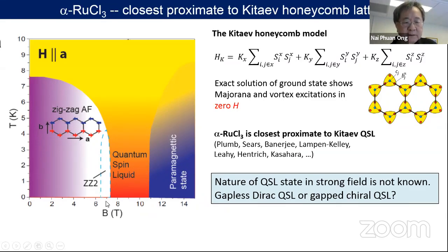At low fields below 7.5 Tesla, you have an ordered state rather than a spin liquid state. And the ordered state is comprised of a zigzag pattern parallel to what's called the zigzag direction, right? Just like in graphene, zigzag means it's going zigzagging here, parallel to the field. And this is called the A-axis in ruthenium chloride. The perpendicular direction, still in the plane, is called the armchair, right? Why? Because this looks like an armchair, right?